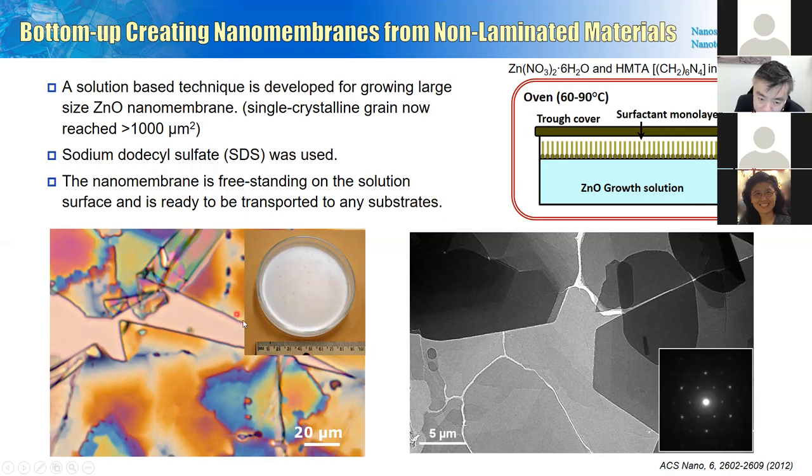There are just some cracks induced by the strain. But once we put it in the TEM, we can see the single sheets are very large in this sort of single crystal. However, they're pretty thick. They're actually hundreds of nanometers in thickness. And in the X-ray diffraction, you can see this kind of multilayer structure. We found out this one is actually a multilayer structure.